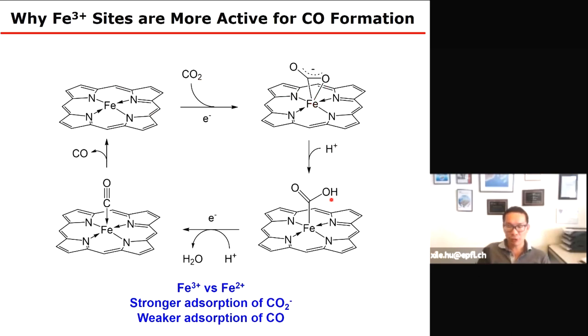Then you have a protonation to make a formyl species. Then you have a proton coupled electron transfer to make water, and you have a CO absorption on the site. And then desorption of CO gives you the catalyst and the product. Now, obviously, if you have iron 3 versus iron 2, for CO release, iron 3 is much better because it has low ability to make back bonding. And that's important because at high current density, CO release can be a rate-determining step. And so we can get really high current densities.